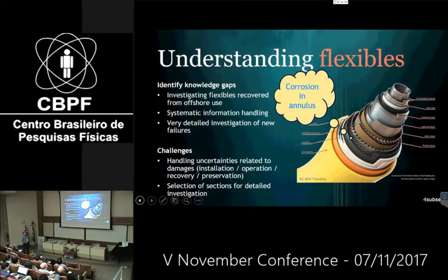My intention here was to talk about the annulus and explaining the layers and all that stuff. That's been done by three or four before, so I don't think I'll say very much about that. Corrosion in the annulus has been discussed quite extensively here. But what is important to say is that this annulus here is due to gas diffusion into the annulus. You need to vent that area, and you vent the gas on the flexible risers top side. So you vent it at the upper end.